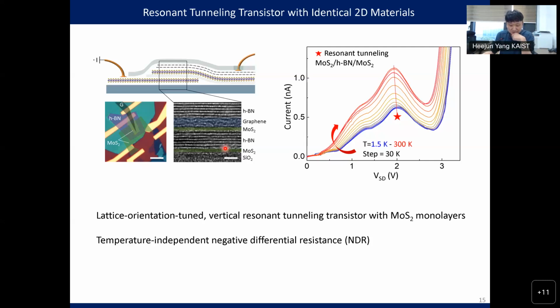And then if we measure the tunneling current between the two MoS2 layers, here we have one electrode, here we have the other electrode. The result is like this. At low temperature and at room temperature, the current increases as we increase the voltage, with some shoulder feature here. And then suddenly the current decreases, even though we are increasing the voltage. This is called negative differential resistance. It is quite weird. Why does the current decrease even though we are increasing the voltage?